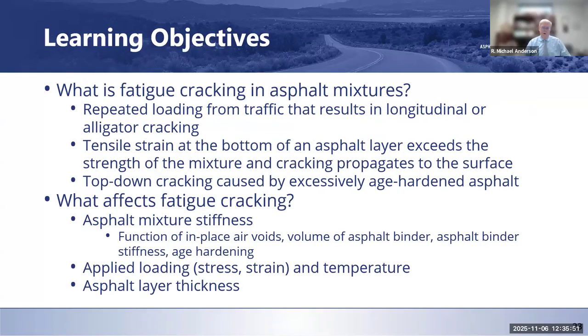So again, what we were looking at is controlling or mitigating the impact of what role the asphalt binder has to play in fatigue cracking. So our learning objectives overall, we wanted to know what is fatigue cracking in an asphalt mixture. We talk about that as being repeated loading from traffic that results in longitudinal or alligator cracking. It's tensile strain at the bottom of the asphalt layer that exceeds the strength of the mixture, and that's where you get cracking that propagates to the surface. If you're talking about top-down cracking, it's caused by excessively age-hardened asphalt.